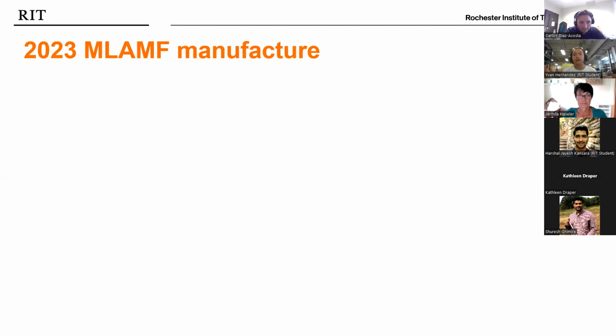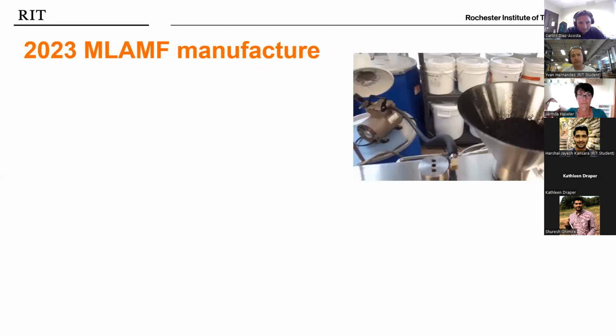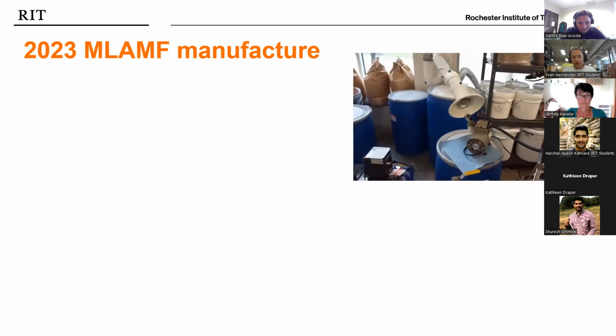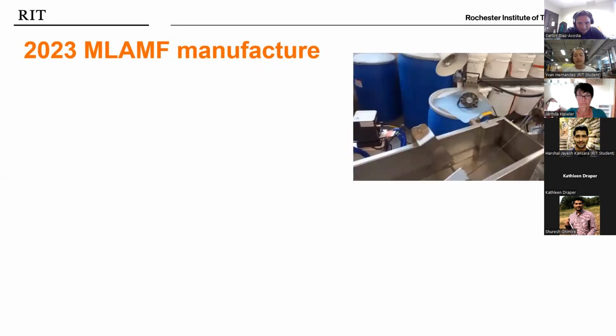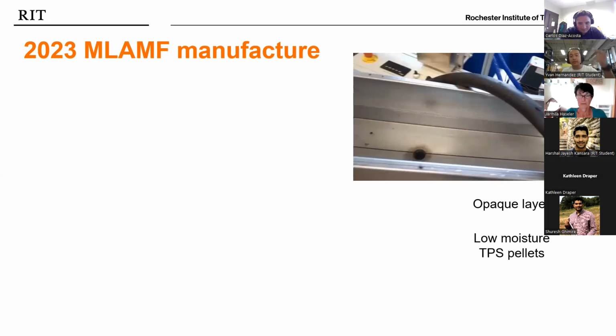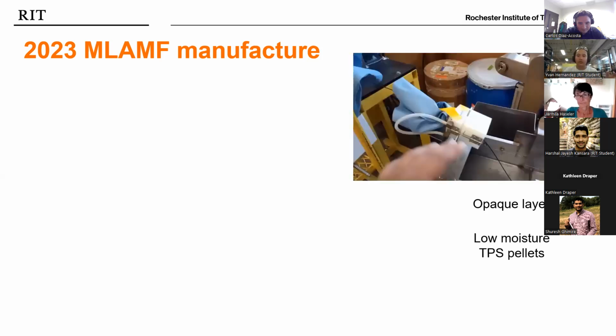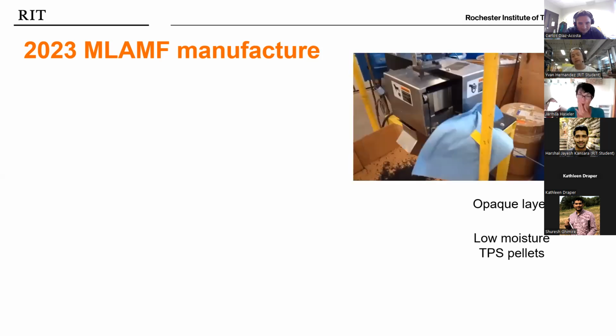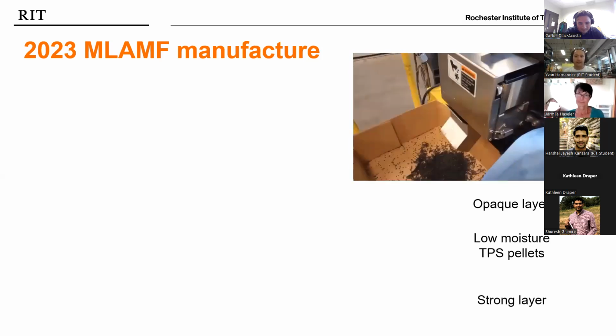Now we could actually make a film. So in the 2023 season, we said we're gonna make this film. So I made a lot of biochar containing PBAT to then layer and make three layers. One that was opaque, so it was gonna have a lot of biochar in to be able to hold the light. One that was the low moisture thermoplastic starch that was able to increase that biodegradability we've been talking about, and a strong layer, maybe one that doesn't have that much biochar, but it will hold and will make all the mechanical work for the laying that we identified during the first year.